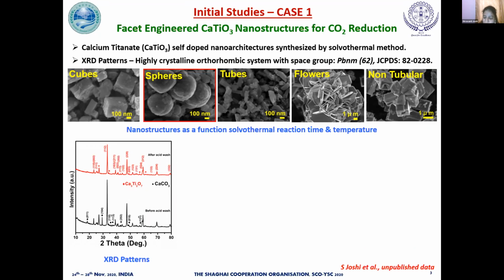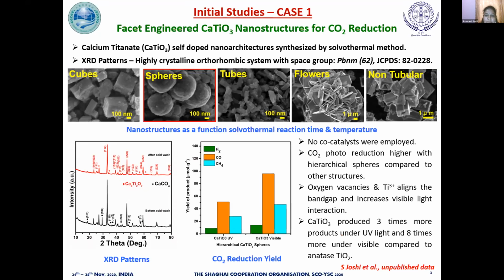Further, here we did not use any co-catalyst and still managed to achieve better CO2 conversion rate as illustrated by this image. As for the conclusion of the study, among all the nanostructures synthesized, only hierarchical spheres gave us good photoreduction capabilities. Further, under UV light, 3 times more fuel-based products were produced, whereas under visible light, we were able to achieve 8 times the capacity. Now, this is when compared to standard anatase titanium dioxide.